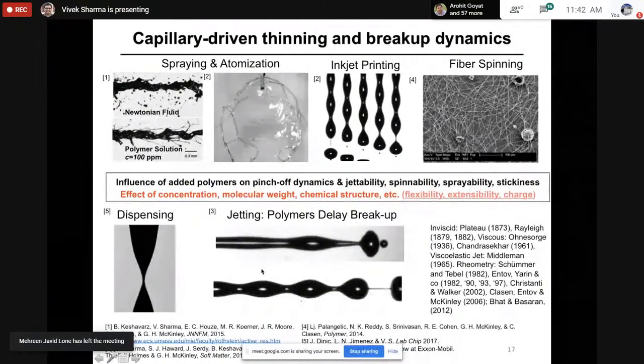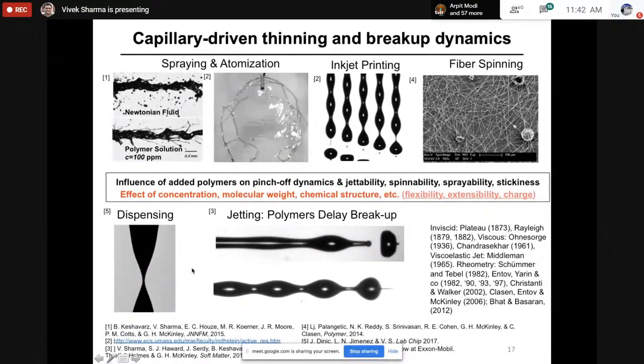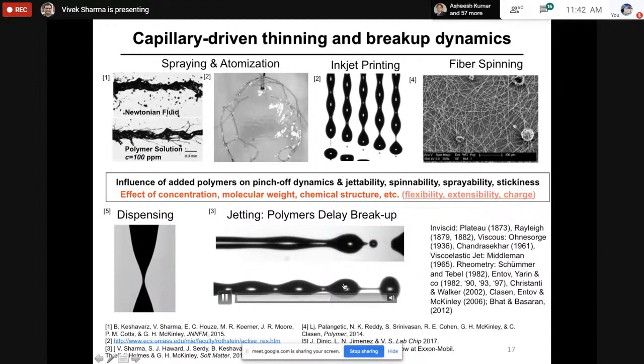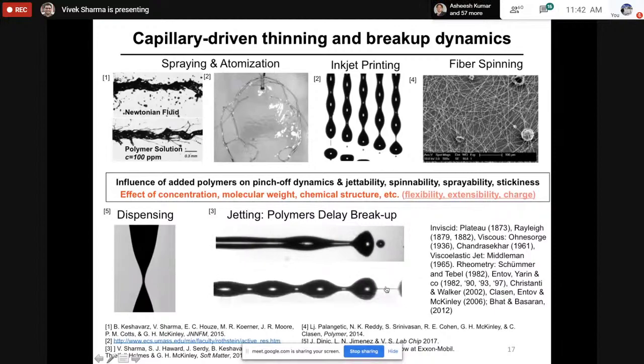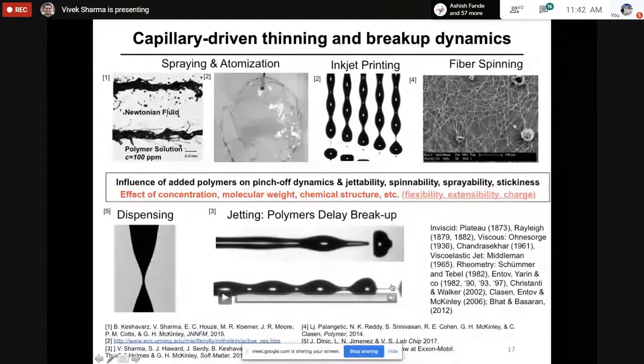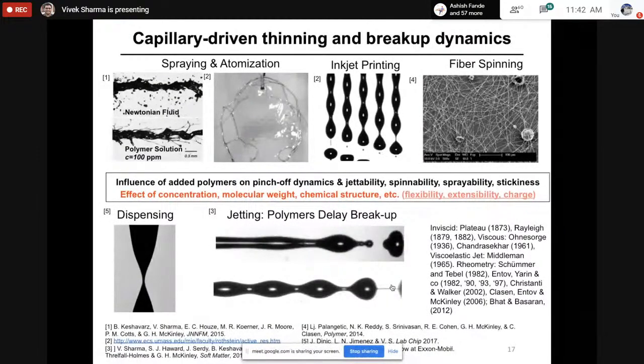If we add a small amount of polymer, 100 ppm or a few hundred ppm, that changes this breakup dynamics completely, and now you don't have any of those satellite drops, and pinching takes maybe slightly longer. If you can avoid satellite drops, that would save a lot of money when you're trying to spray paint things, and it also saves a lot of extra fertilizer or insecticides and pesticides that get blown away because the drop size is too small, so they can't really land on the plant and lead to all kinds of pollution. So it's important to understand how to add small amounts of polymer to control atomization, sprays, fiber formation, jetting, spraying, and that has been motivation for us